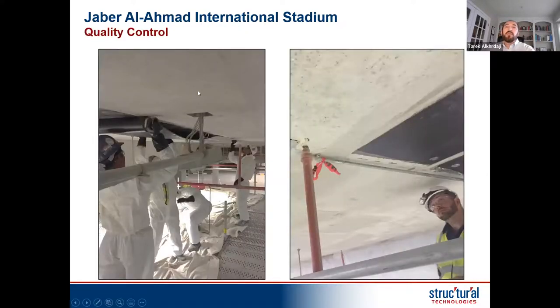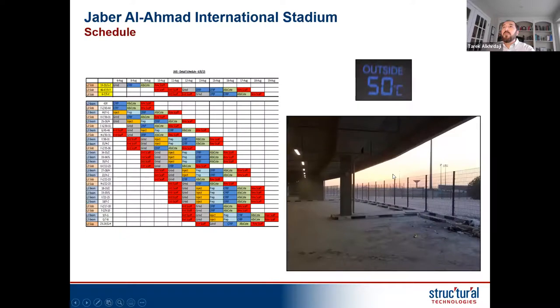Here you can see a crew that was sent, a leadership crew that all came from the US, utilizing local labor and some labor from the US that went there, with the leadership to do this work. You can see here the FRP applied to the surface. The challenging part was the temperature, and I wanted to mention this. There was significantly hot weather during the day, and then it really cooled down in the evening. And the nice thing with epoxy is that it cures quickly, right? When it's at a higher temperature, it starts curing faster. In reality, within 24 hours you can achieve full cure of the epoxy.